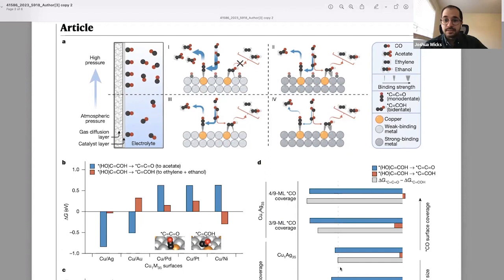Exactly. So we started off by examining some of the proposed reaction pathways from our colleagues in the academic community who spent a lot of time thinking about reaction energetics and all the different combinations of intermediates and adsorbates that lead to a variety of different products. And we noticed that the configuration or orientation of the adsorbate on the catalyst surface, when we're in a multi-carbon adsorbate regime, can take on two different modes. The first is a bidentate mode where two carbons are adsorbed to the surface and you might have other oxygens or hydrogens joined to that adsorbate. And actually, a lot of the pathways do follow this scheme. And then the other mode is a monodentate adsorbate, where you still have two carbons in the adsorbate, but only one of those carbons is adsorbed to the surface.